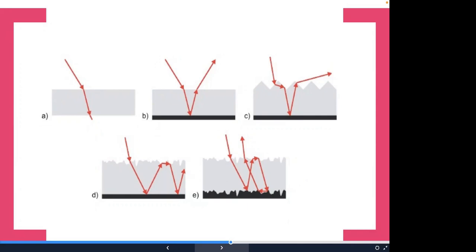So there are two reasons. First of all, one problem with this, which we didn't talk about too much, is something called surface recombination. When you texturize the surface, you're damaging the crystal structure of silicon. That means you have defects in the crystal structure, and this is bad. These defects essentially give rise to intermediate energy levels in the band gap, and the electron holes that are generated in the silicon will get trapped there. They will not reach the contacts and contribute to current. And this is the recombination loss.